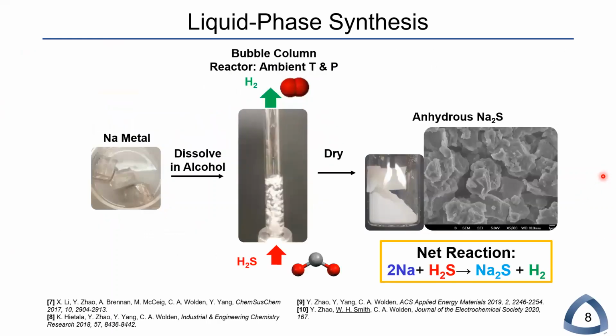On the other hand, the liquid phase synthesis is outlined here. The process consists of first dissolving sodium metal in an alcohol to produce a sodium alkoxide precursor solution and producing hydrogen gas in the process. Next, the sodium alkoxide solution is contacted with hydrogen sulfide gas, during which the hydrogen sulfide is completely consumed, reacting with the sodium alkoxide to form a sodium sulfide solution and regenerating the original alcohol.